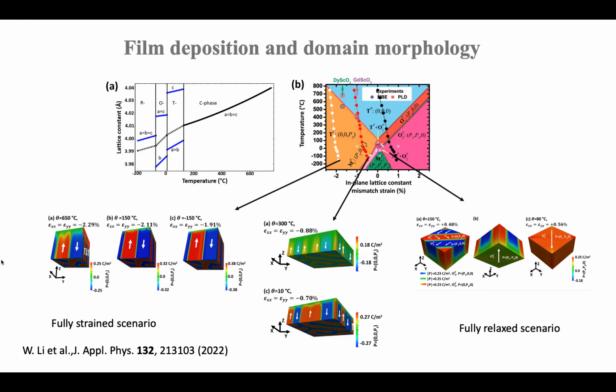And it turns out that if you're fully strained, you maintain the tetragonal phase all the way through. At any temperature, it's all tetragonal BaTiO3. However, if you're fully relaxed, you actually can end up in what you would call AMM2, right? It's an orthorhombic type thing, so your polarization actually isn't out of plane, but it's a different phase, right? And so we think we're somewhere in the middle. The top has an in-plane polarization, and the bottom is tetragonal.